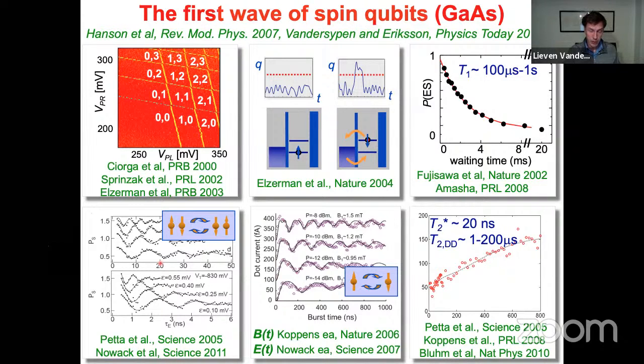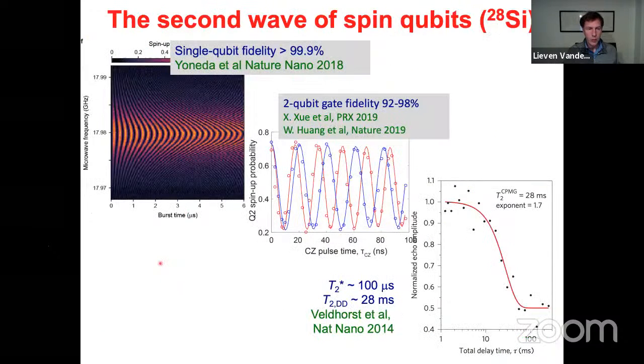So this was the first wave of spin qubit development based on gallium arsenide. In my mind, this was kind of a dead-end road because of the short dephasing time, but all the concepts were shown to work. Now the field got a second boost when, as a community, we learned to build suitable quantum dots in silicon and even build isotopically purified versions of this, where the silicon-29 atoms that also have a nuclear spin are largely eliminated, and mostly what remains at the location of the quantum dot is silicon-28, which has no nuclear spin. And so this problem of hyperfine induced dephasing is immediately gone.